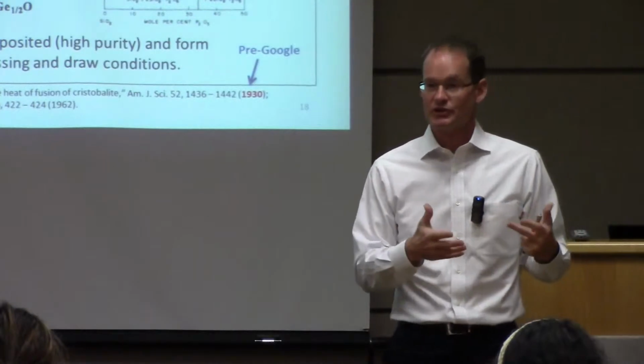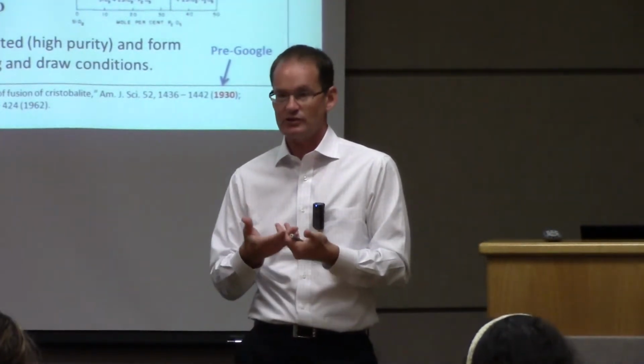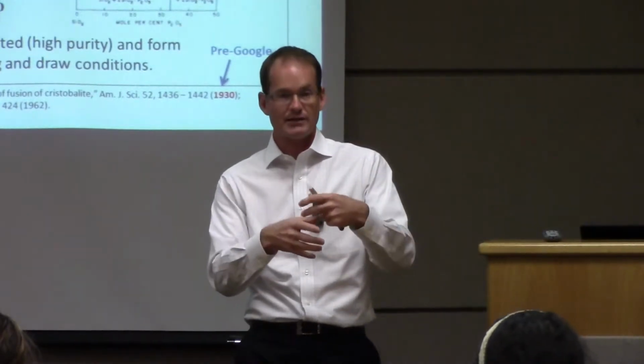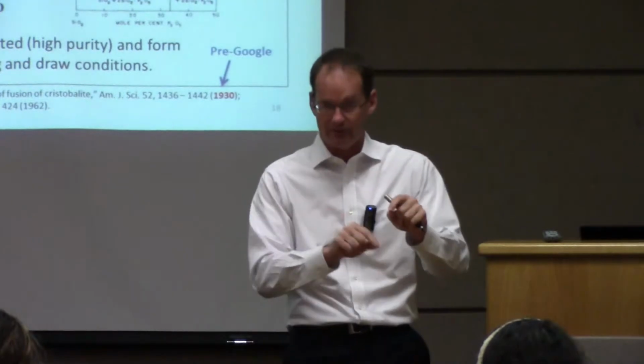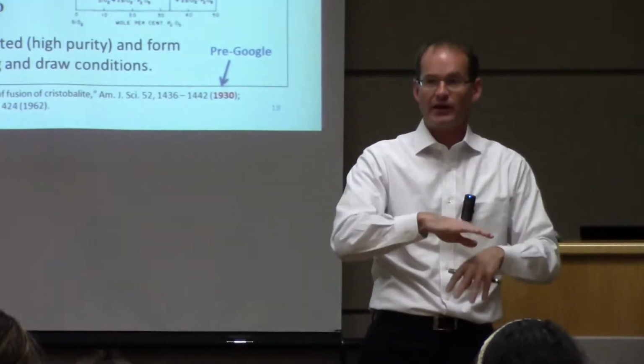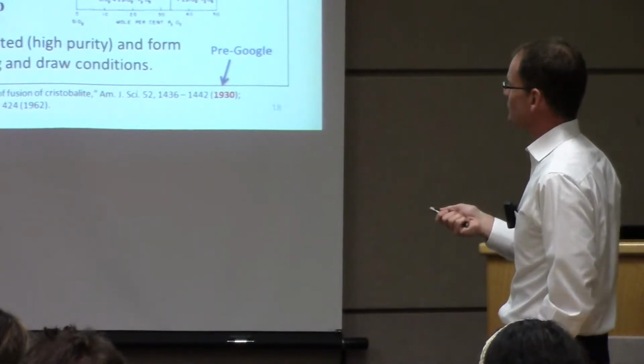You, of course, have other systems that mix beautifully well. Those are obviously the ones you want to stick to, because you're going to want a glass that is homogeneous. As the light goes through it, it just sees one thing. It doesn't see this material, then that material, then this material, because it's going to bounce around and scatter, and all your light's going to be lost. Okay? And again, you're going to see a few things like this.